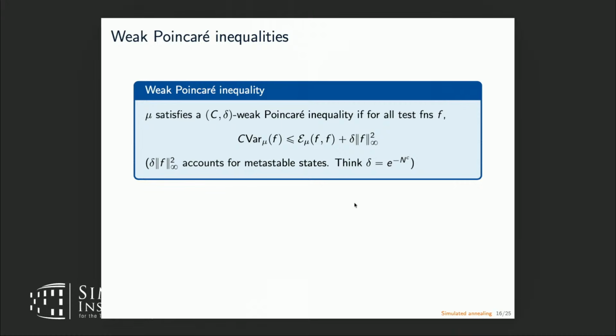So one of our main ideas is to look at what's called weak Poincare inequalities. So this is a variant of a Poincare inequality that turns out to be more tolerant to metastable states. So it includes this extra parameter delta. And the statement is like a Poincare inequality, except there's this extra error term that depends on delta and on the infinity norm of f squared. So this is the term that will sort of account for the metastable states. As for how big things are, think of c as like a big constant and delta as something that's extremely small, like maybe a stretched exponential type of size.